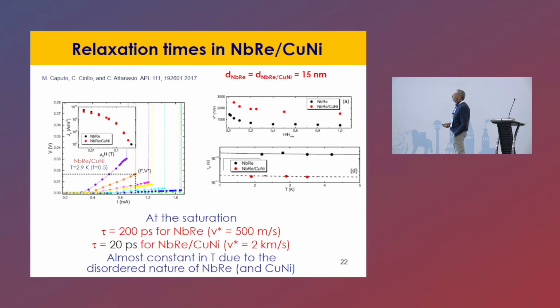Since real superconducting single photon detectors have been made out of niobium rhenium, both nanowire and micrometer strip single photon detectors, we want to propose now what happens if we put copper nickel on the niobium rhenium. And then we fabricated these bilayers. We measured the critical velocity, and you see here again that the results are very encouraging. So the critical velocity is more or less 2 times higher in the case of niobium rhenium copper nickel with respect to niobium rhenium, and also I think more, maybe 4 times.